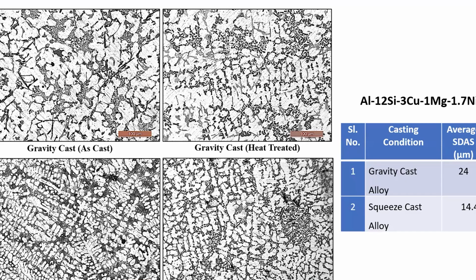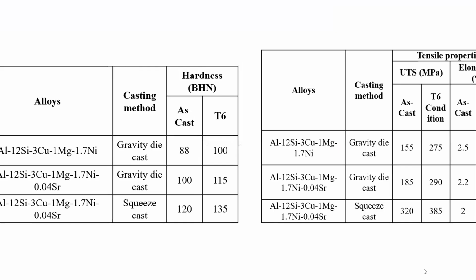We have studied a lot of alloys, and we observed that compared to gravity casting, in squeeze casting the grain size is reduced. That means the alpha grain size is reduced, and the dendritic arm spacing between the dendrites is also reduced remarkably. So this will be reflected in your properties.